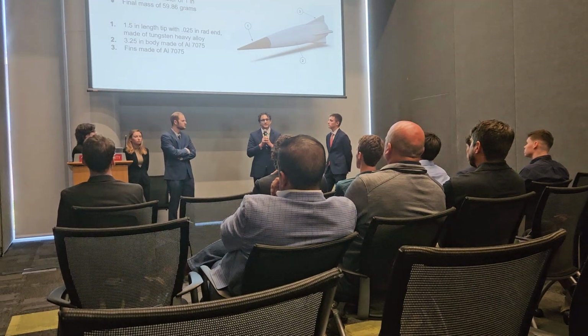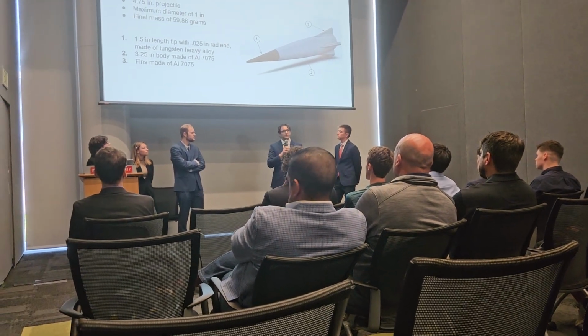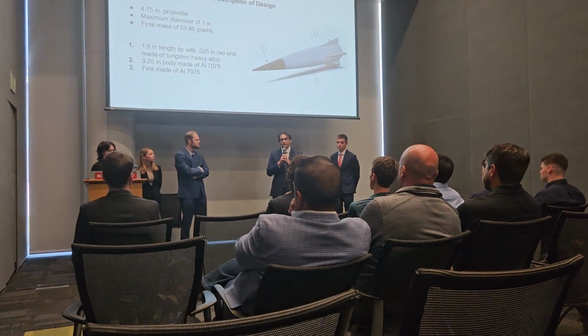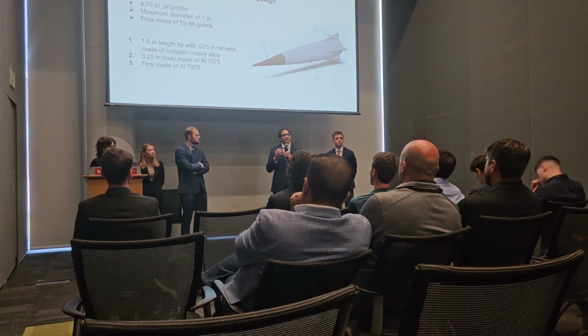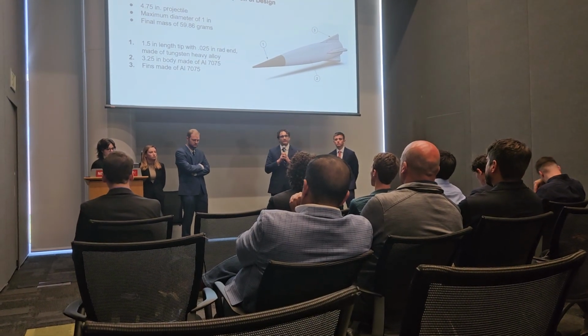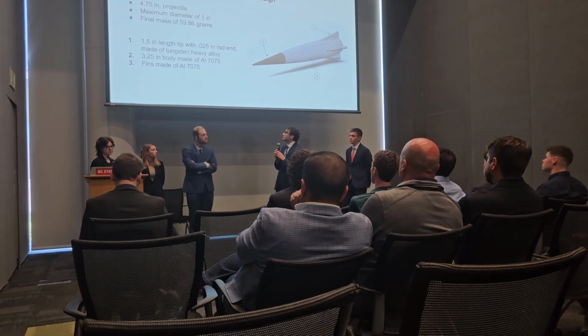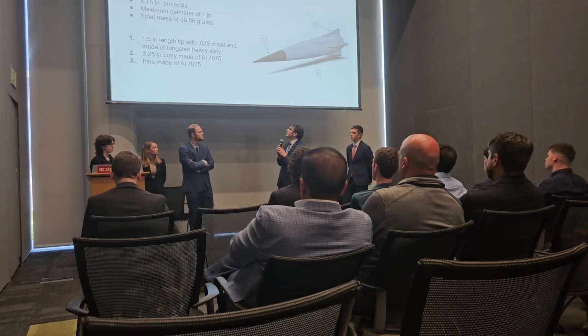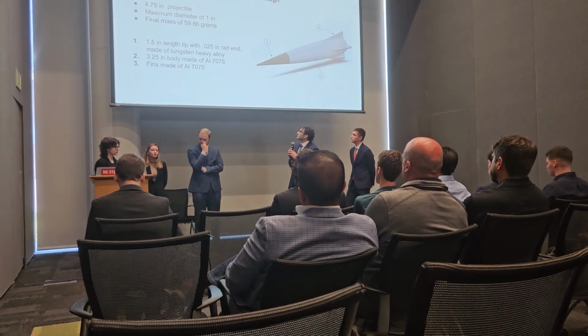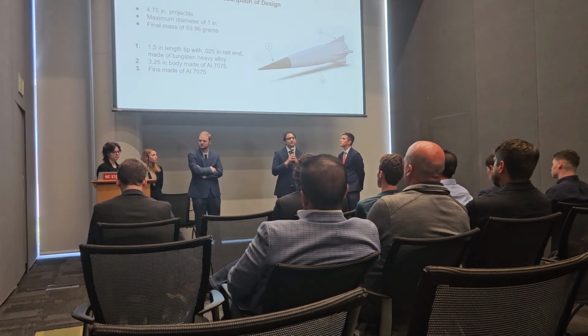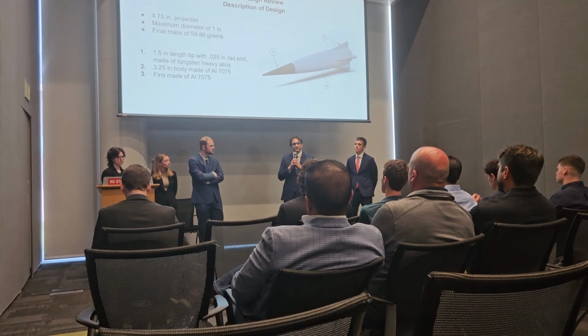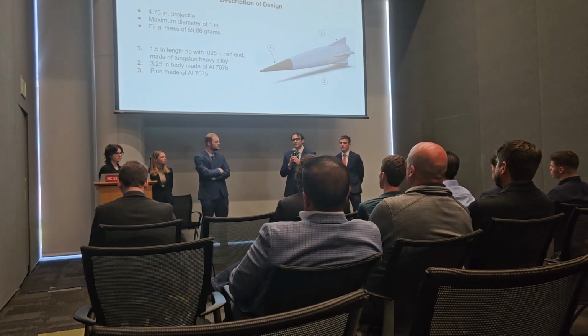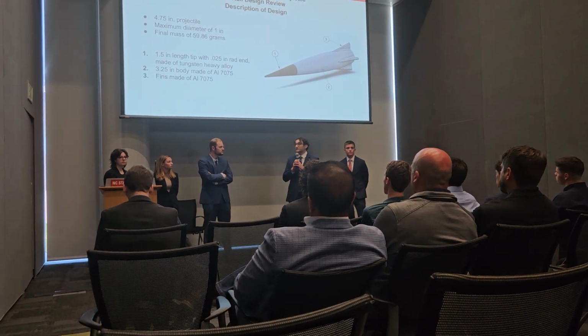Get it as close to the 60 gram limit as we could, because we believe that the mass would be the most important in determining how much momentum the projectile would have and how well it would be able to penetrate the target. So, we wound up manufacturing the tip with a 0.025 inch end, and that was ultimately just for manufacturability, to make sure the tip wasn't too sharp and the tip was actually feasible to manufacture.